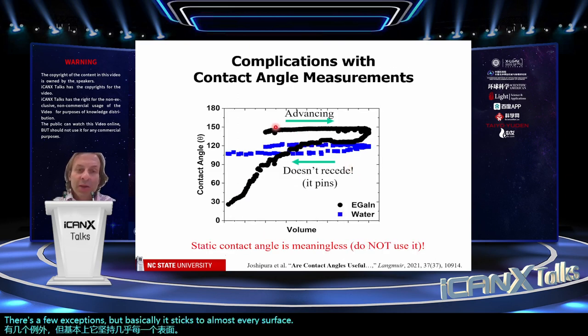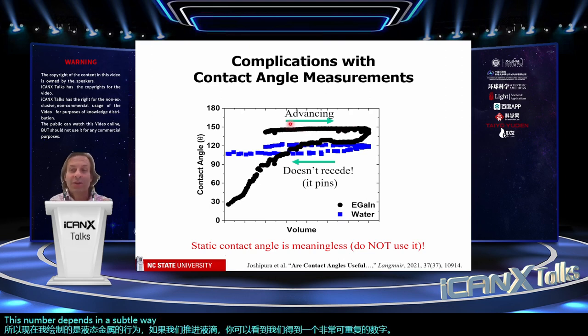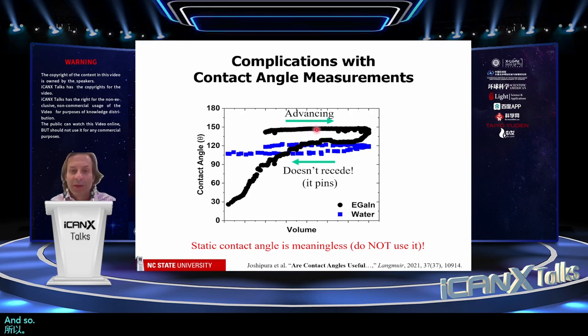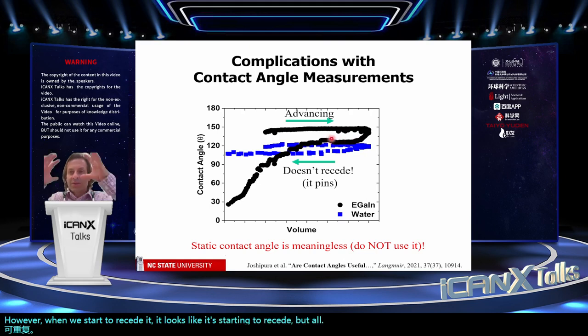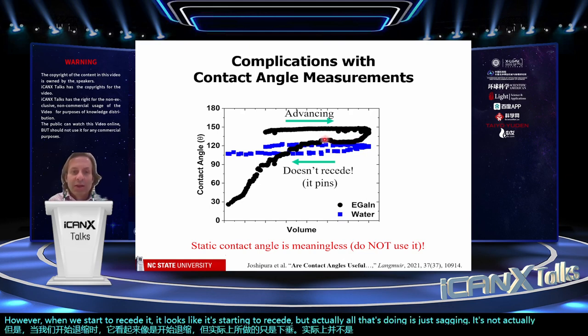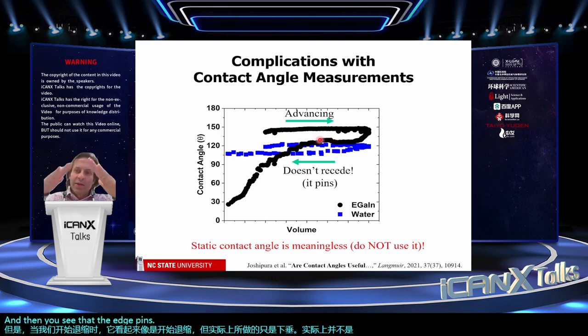So now what I'm plotting here is the behavior of the liquid metal. If we advance the droplet, you can see we get a very reproducible number, about 150. This number depends in a subtle way on the substrate, but it's always high. It's always between 140 and say 150. And so my suggestion is if you want to take a contact angle, to use advancing contact angle because it's actually reproducible. However, when we start to recede it, it looks like it's starting to recede, but all that's doing is just sagging. It's not actually receding. And then you see that the edge pins and the angle gets smaller, but it never recedes.